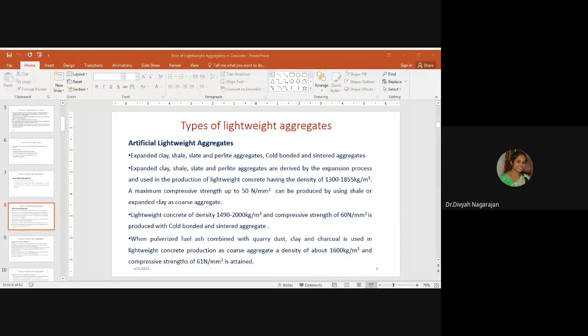In expansion process, the aggregates are manufactured by applying heat on the aggregate to a temperature of 1000 to 1200 degrees Celsius. Thereby, the aggregates are expanded due to entrapped gases. Now, in agglomeration process, finer particles are bound together and hence coarse aggregate is formed by mechanical means. In this method, the moisturized fine particles together form pellets sintered in the furnace to an appropriate temperature. Expanded shale, clay, slate come under this category.